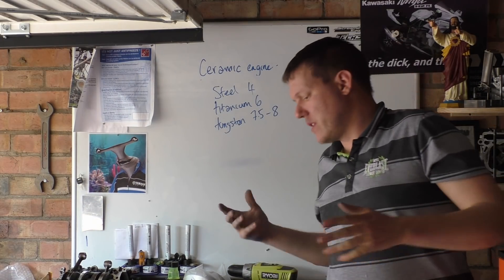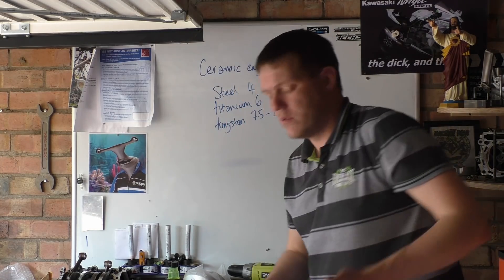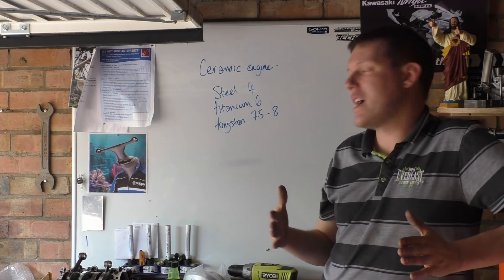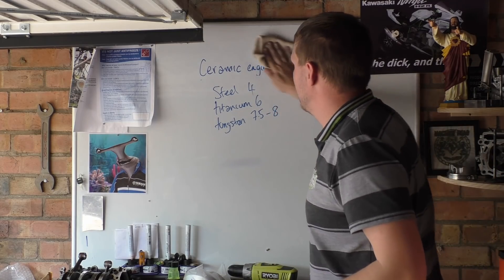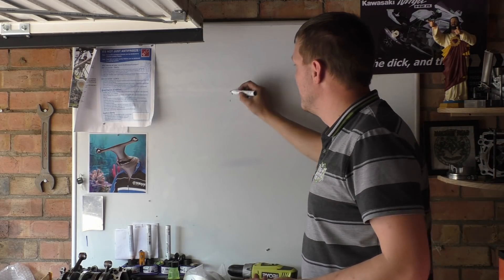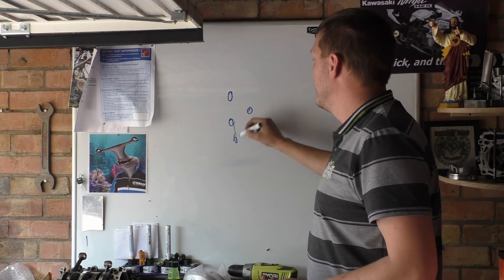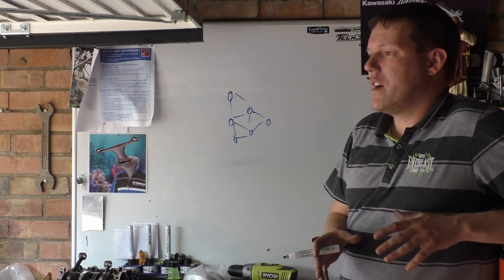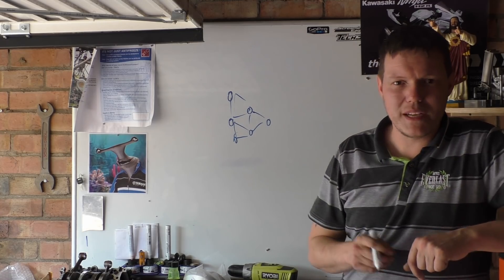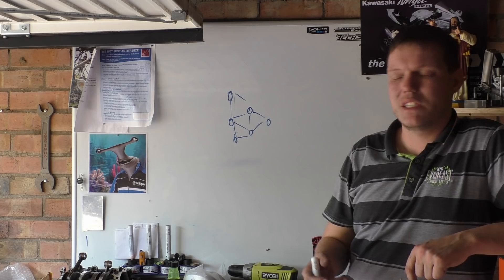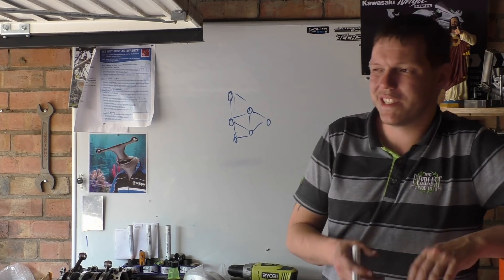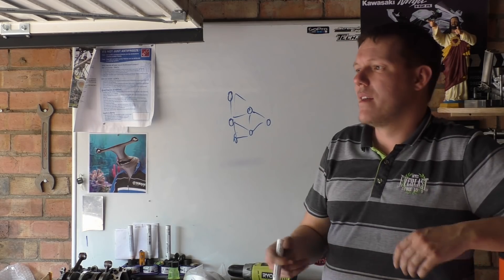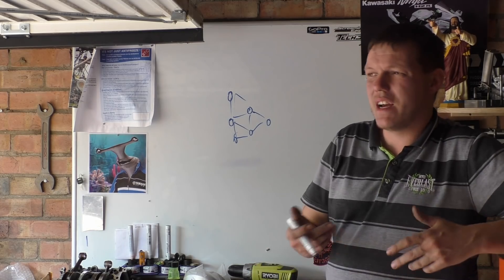Ceramics — they are a different material and they do have their uses. We use tungsten carbide for cutting tools, because if you have a harder material, the hardness of a material is how well it holds on to all its atoms. If you have atoms all locked together really nicely with a good bond between them, they can hold an edge better. So we use tungsten carbide — which is stiff as hell — for cutting tools. But tungsten carbide shatters and breaks, whereas steel will dull and round off, even hardened steel.